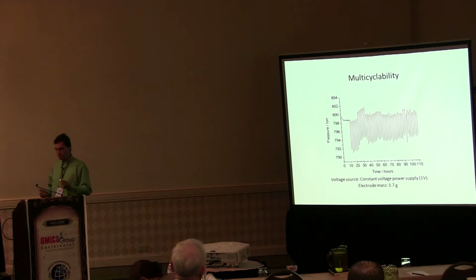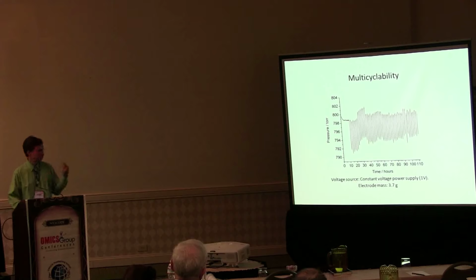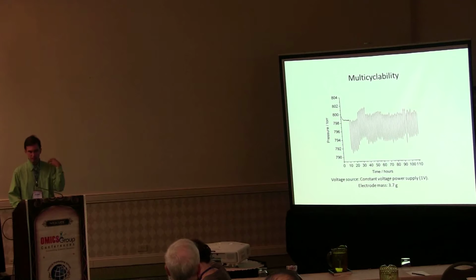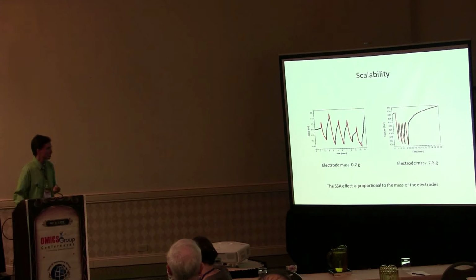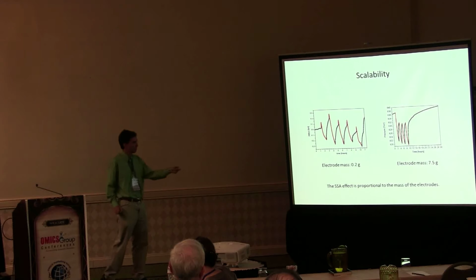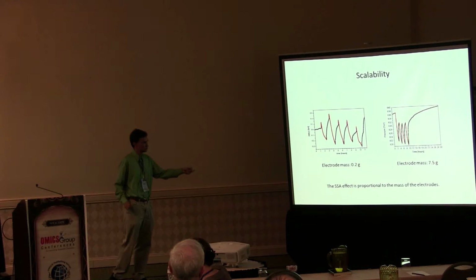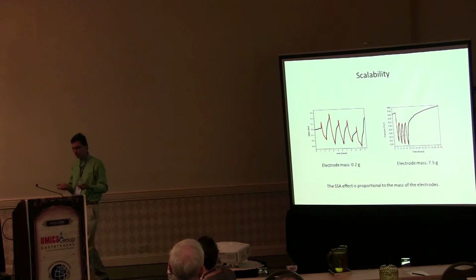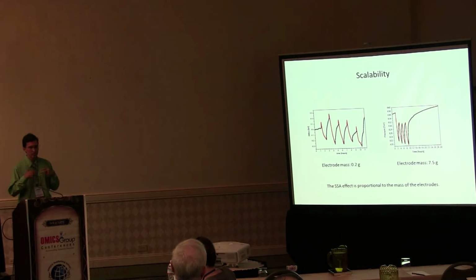Having established this result, we were interested in the question: is this technique scalable? So we changed the mass of the electrodes. We went to electrodes with a larger mass and with a smaller mass, respectively, and measured the pressure changes. We observed that the pressure changes scale proportionally with the mass of the electrodes.